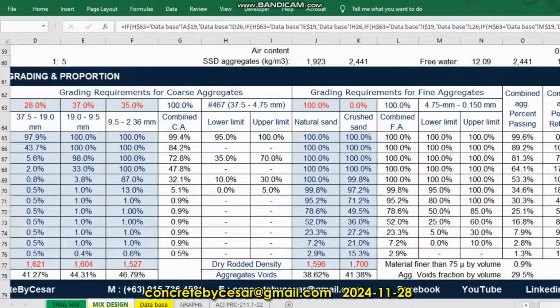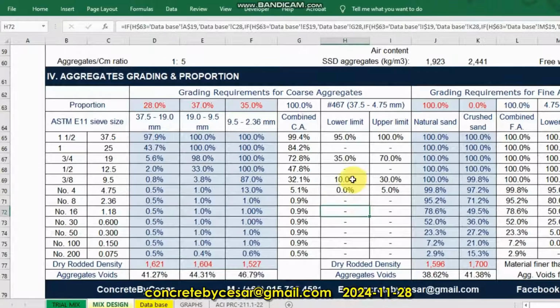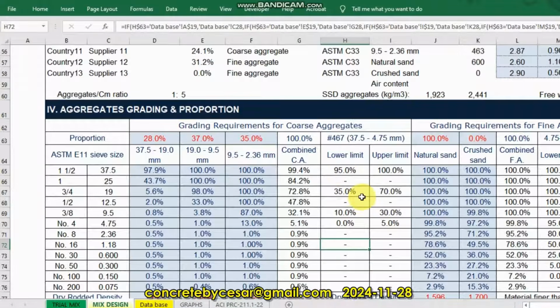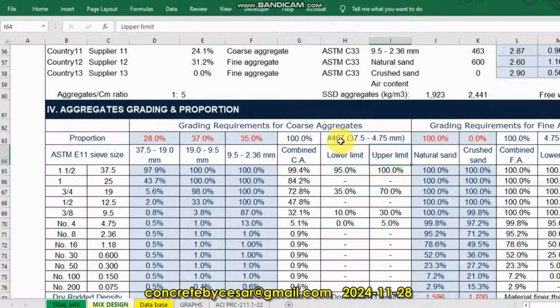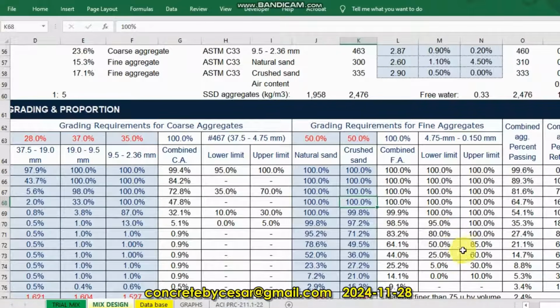So you don't have to worry in case the specification really calls to be in line with this lower limit and upper limit according to ASTM C33. Then you have to start from here. So you have to manipulate these values or this proportion. If you have two sizes of sand, one is natural, one is crushed, you can also write here, for example, 50% here, another 50%. Then you will check the lower limit and the upper limit if it's inside the limit. So one by one you have to check in case you need.